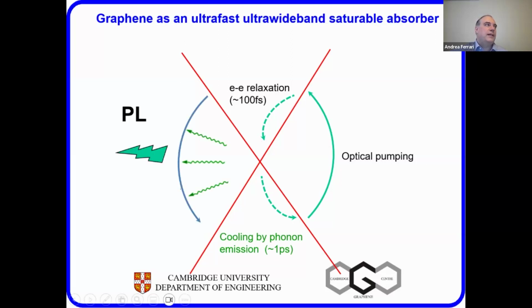Actually, quite interestingly, but I will not discuss it in detail, they can also recombine and emit PL. This is ultra-fast PL. And by the way, because of the interaction of electrons, the PL can exist, and the energy of the PL can be higher than the incoming optical pump, which is quite weird because usually it's lower, but some electrons can be excited to higher energy and then recombine.